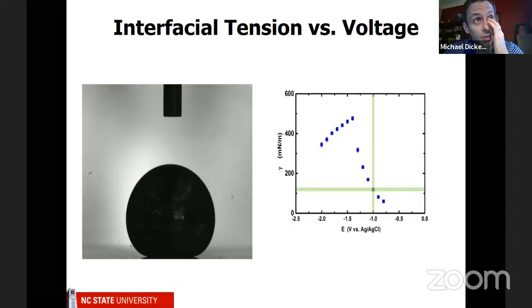So the short answer is we've tried it a little bit, and the thinking is that if you imagine an AC voltage, say that this is 0. When you go to positive, you oxidize the metal as long as you get a high enough voltage, and then when you go to the negative part, you could reduce it. Now I'm talking about an electrolyte. If you don't have it in electrolyte, it's probably not very interesting. And so we've done a little bit of that because the thinking was that it would help control the shape. And I would say that we were never really able to control it very well, so it didn't work as well as I hoped. But that's not to say that it's not worth exploring again.